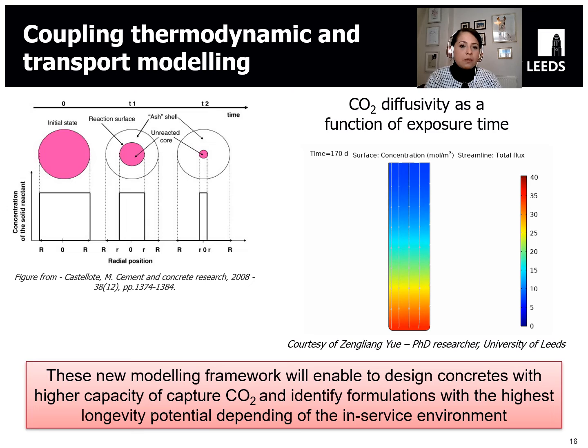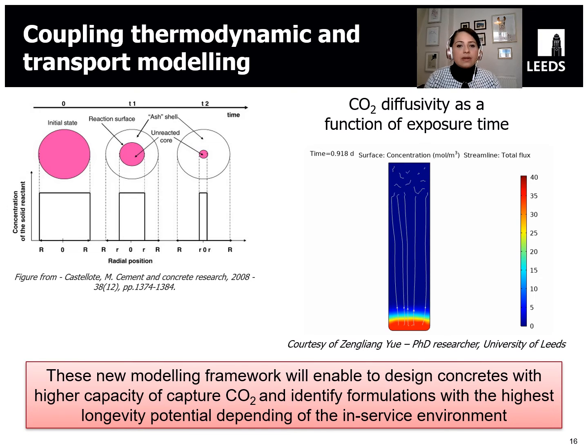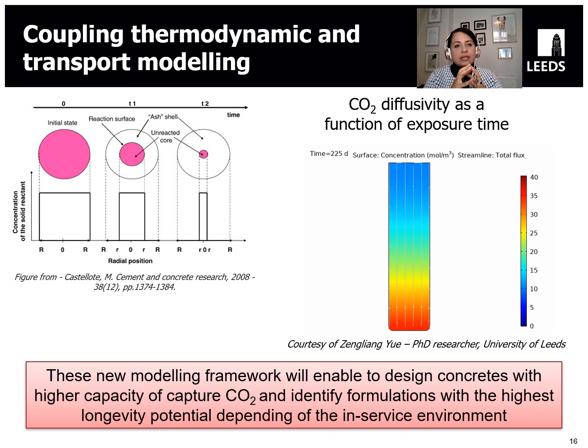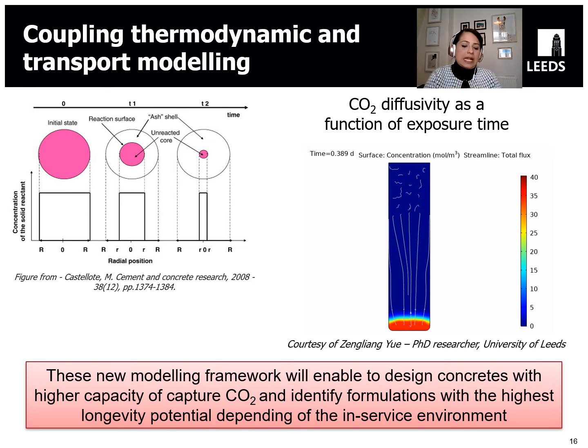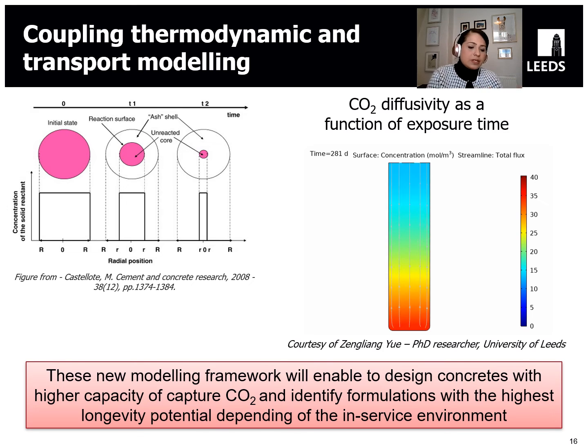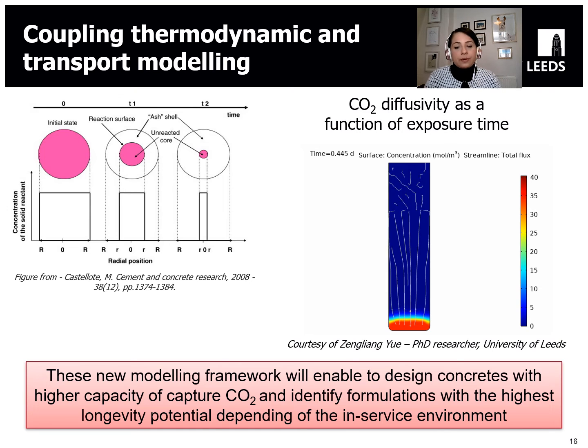The concept we're using at the moment is not very new. It has been proposed for many years, but it's like the shell or the unreacted core type concept. So what we are assuming is that we will have these different layers of carbonated material, each of which we are assuming will be of different ages, will have a specific phase assemblage, a specific porosity or tortuosity, and therefore carbonation in each of these layers will occur in a different manner, accounting for the two concepts of changes in phase assemblage and solution chemistry plus porosity distribution as the reaction progresses. So hopefully in a couple of years I will be able to share some of the outputs of this amazing job that Zhengliang is currently doing.